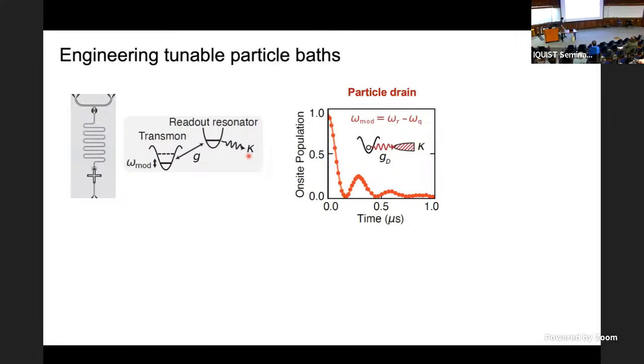This first process, what we do is we actually modulate the on-site frequency at a frequency that's the difference between the resonator frequency, omega r, and the qubit frequency. This puts sidebands on the particle in the lattice so that the particle sometimes lives at the frequency of the resonator. So you've now parametrically turned on a resonant interaction that allows particles in the lattice to resonantly leak out of the system through this resonator. So you can see in this example, if we start with one particle in the lattice site, we turn on this bath interaction, and you can see it quickly decays to the ground state and will stay there as long as your bath coupling is on.